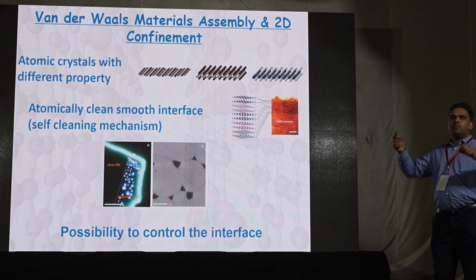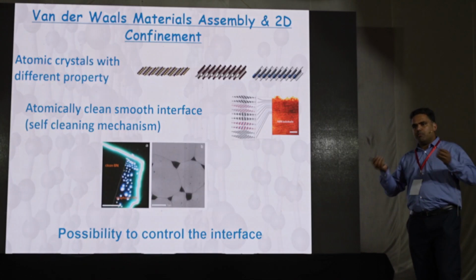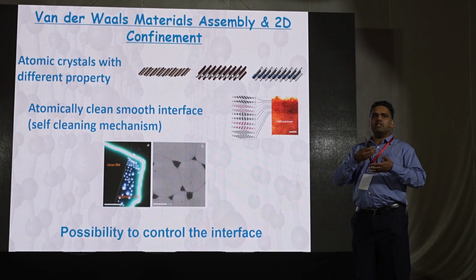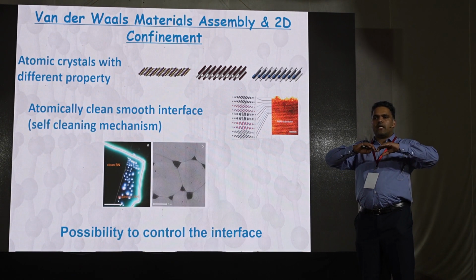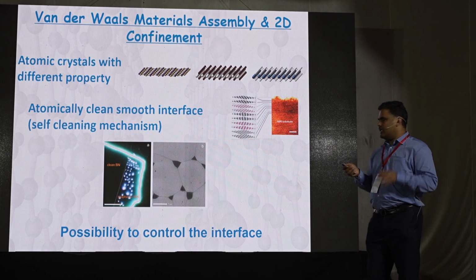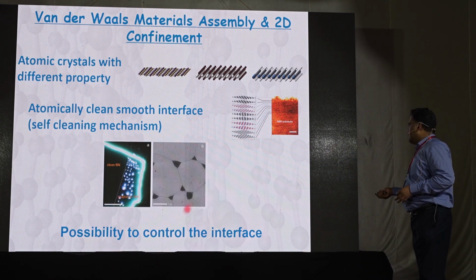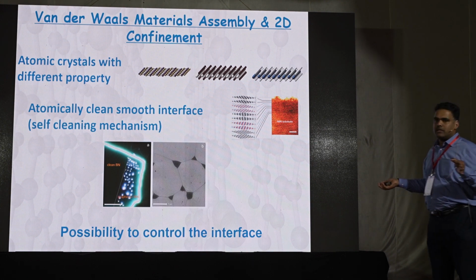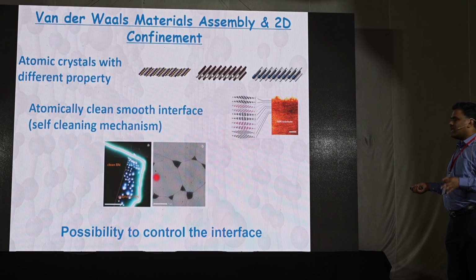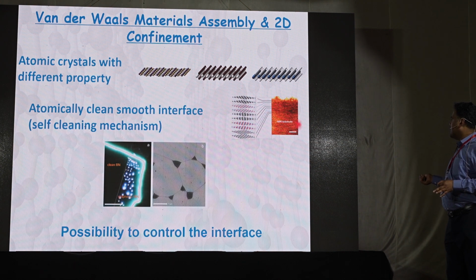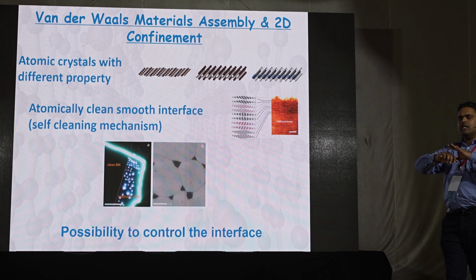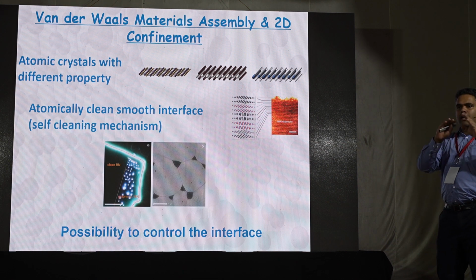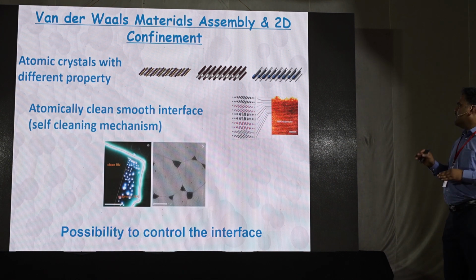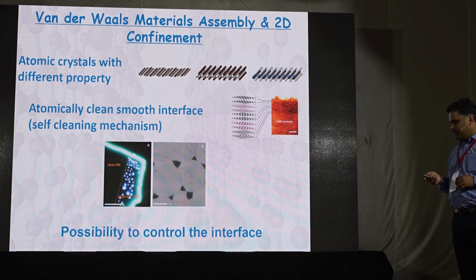So what happens is that when you put some molecule, an example is water. If you put water or organic solvent or salt solution between 2 layers, the layers actually try to squeeze this molecule into small pockets. So that is what you see here. The black ones, these are pockets of some molecules. The other regions are clean interface. They are atomically clean. Basically, that means there is no dirt or no molecule in this clean region. And in these pockets, a small number of molecules are confined within 2 layers, and then interesting chemistry can be observed there.